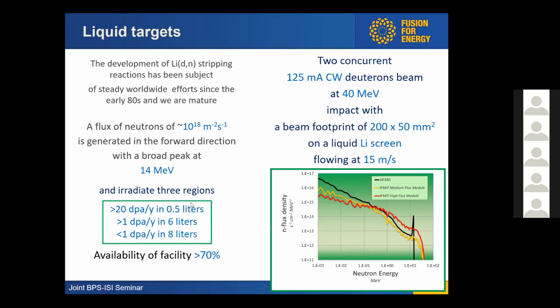And the idea with this is we will have a high flux test module in which we will have 3 different volumes: a very narrow, small one of half a liter that would be enjoying, let's say, 20 dpa per year, that would match that of a demo reactor. If we go for 3 gigawatts or 2.5 gigawatts thermal power, 1 dpa per year in a 6-liter volume, and less than 1 dpa per year in 8 liters. One of the challenges is also the availability of the facility to avoid this point that I mentioned before about hysteresis, which should be above 70%, which is also very challenging.